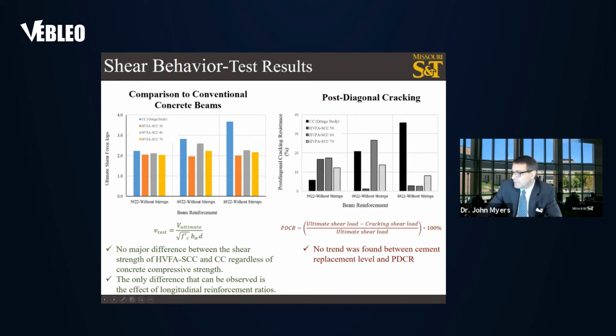There is no trend found between the cement replacement level and the PDCR. And the only difference that can be observed is the effect of longitudinal reinforcement ratios.